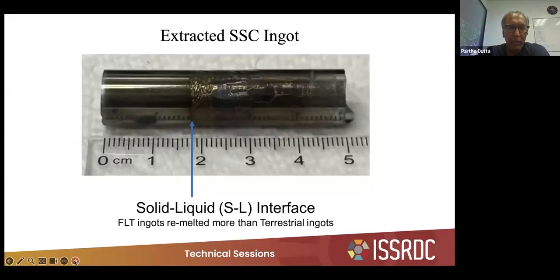Then we started to dig deeper into the hardware, and this is the crystal that was regrown. Part of the crystal was remelted and regrown in the MSG glove box in the SUBSA furnace. And we tried to unravel all the mysteries and the significant things that we learned through this Mission 1. One of them is shown on this slide. We can see the solid liquid interface, which is clearly seen and highlighted here. And to our surprise, the predictions that we had on the crystal and the location of the solid liquid interface was within a millimeter or two from where we expected it to be. So that shows that the crystal growth conditions that we had developed terrestrially for the microgravity experiments were precise enough, and that provides a strong background for scaling up these kinds of materials in space going forward. Next slide.